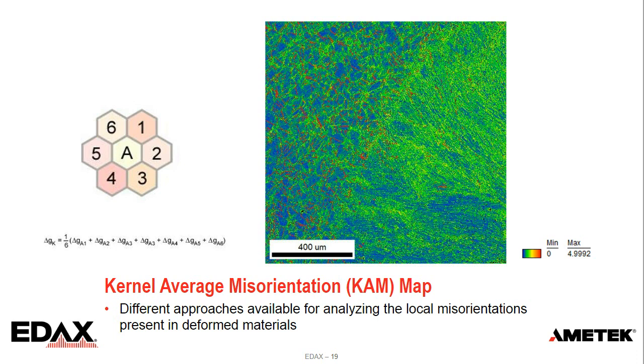So the color scale used here, blue is basically zero misorientation. Red would be essentially 5 degrees, and we often use 5 as a cutoff. After 5, it starts to be more of a higher angle, maybe a grain boundary. We can see in this map the weld area has a higher KAM value. It's a little brighter in the top right than on the base metal to the left, but there's still a good deal of KAM strength throughout the microstructure. We'll show some other examples of how we can count these misorientations, and also some examples of going to higher precision with HR-EBSD.